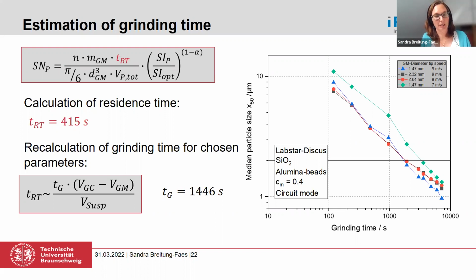In this case, we run the mill in a circuit mode. And in circuit mode, the residence time is connected with the grinding time, as you can see here by the grinding chamber volume, the volume of the grinding bead filling, and the volume of the suspension itself. And then we came up with a grinding time of roughly 1,500 seconds. And when you compare it to the results here, you can see, okay, it seems to work pretty well. Yes, because I know this mill and I had the one or the other experiment available to prove if this is true. But if you take, let's say, a tenth more, you might come up with a grinding time of, let's say, 100 seconds or even 10,000 seconds. So here you need to be really sure what you do.